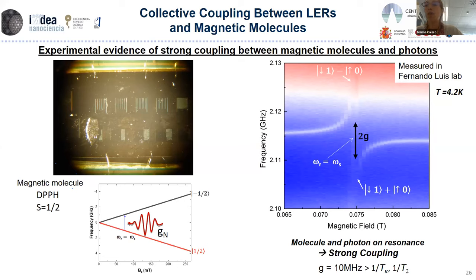The coupling between the photons in the cavity and the magnetic molecule is given by the distance in frequency between those two new energy levels. As we can see here, we achieve some coupling between the magnetic molecules and the photons in the cavity, which in this case is higher than the photon decay rate and the decay rate of the magnetic molecule. So this means that we can achieve a strong coupling between both systems.